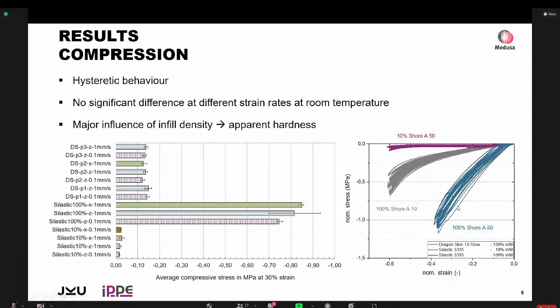And we can see, because we need these very soft brain lobes, we don't have to necessarily go to a very soft silicone elastomer, which is a bit harder to print. We can also just reduce the infill consistently, and then we get a way softer behavior. This seems logical so far. We can also see hysteretic behavior, and we tested at different strain rates, but we couldn't see any significant difference. So this is also nice for our application.